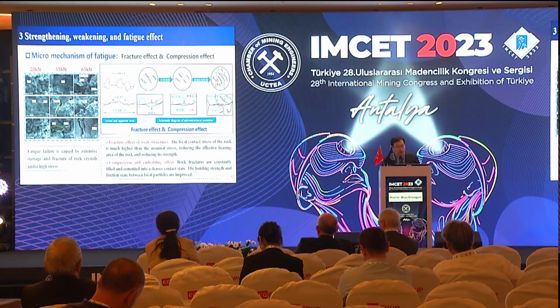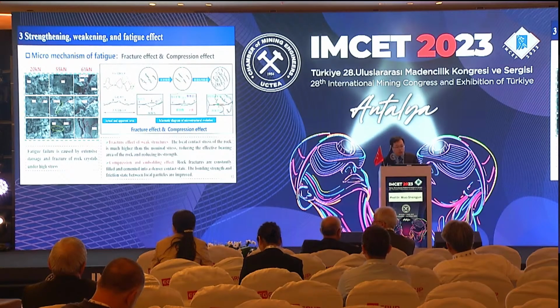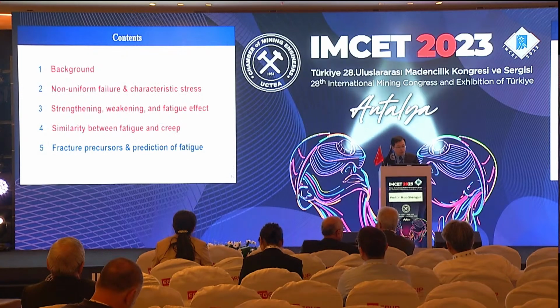Fatigue failure was caused by widespread damage and fracturing of rock crystals under high stress conditions. Therefore, we propose the concepts of weak structure fracture effect and the compaction and embedding effects in siltstone under cyclic loading. In the fourth part, we studied the similar mechanical behavior between the fatigue and the creep test.